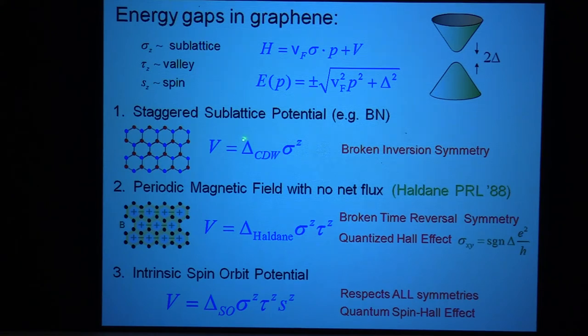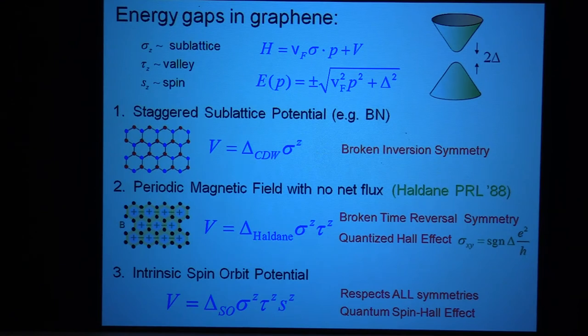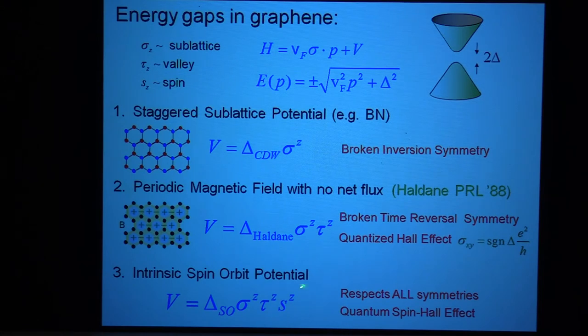The problem is both of these break a symmetry that graphene has, so real graphene shouldn't be in either of these two states. But it turns out that if you have a mass term just like the Haldane mass term but with opposite signs for the up and down spins, then this respects all of the symmetries that graphene has. The problem with the Haldane term is that under time reversal symmetry it was odd — it's like a magnetic field. But under time reversal the up spin goes to the down spin, so putting the spin in here fixes that. This involves an interaction between the orbital degrees of freedom and the spin degrees of freedom, so it requires a spin-orbit interaction, and this interaction should in principle open up an energy gap.